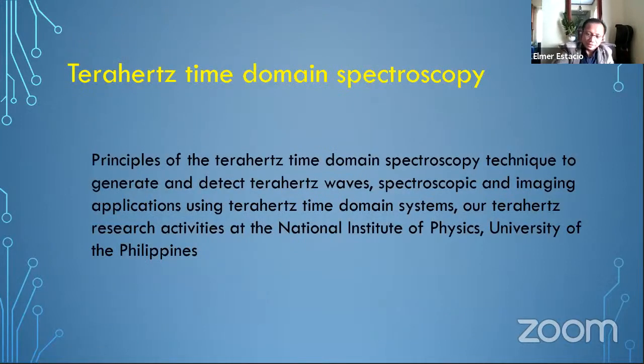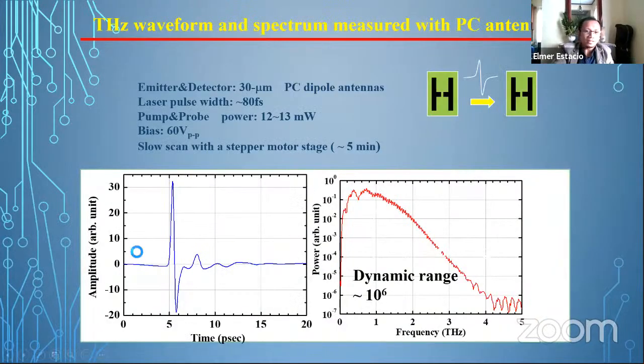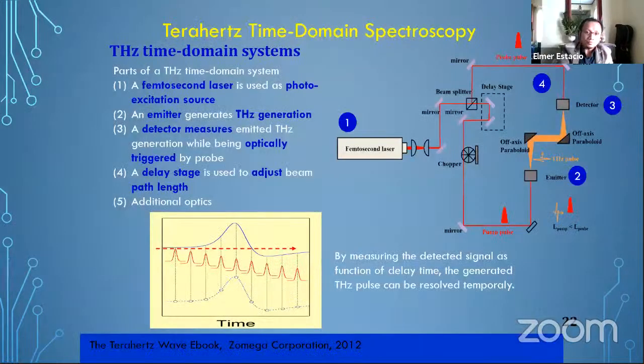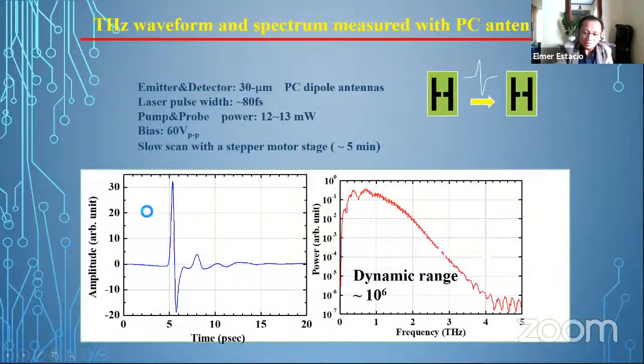So in the next few slides, I'm going to introduce terahertz time domain spectroscopy as we use it to generate terahertz radiation, some examples of how we use terahertz light, not in UP but elsewhere, and a quick rundown of what we do at the National Institute of Physics. Typically, as I showed a while ago, this is a terahertz radiation pulse from a semiconductor, and this is typically seen for sub 100 femtosecond pulse widths, having optical pump powers in the milliwatt range, and this corresponds to a terahertz beam that would have a spectral range of about 3 terahertz, having 6 orders of signal to noise ratio. How do we measure this terahertz pulse in the first place?